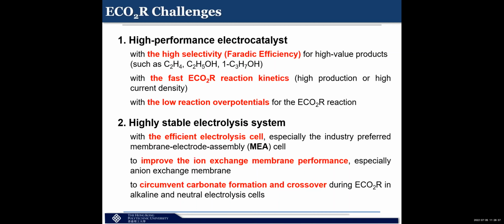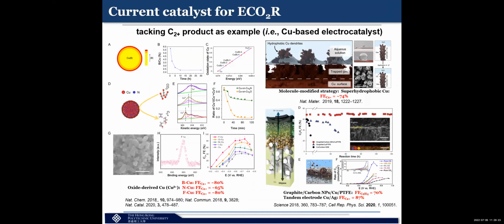But the other very important challenge is this carbonate formation or crossover in the normally electrolysis cell. They will either use alkalis or neutral type of electrolytes. So that make it very difficult to stop the crossover and stop this carbonate formation, because once the carbonate forms, it will block the cell, and then it will cause flooding, and then eventually it will shut down your cell. Okay, so the stability of the cell becomes very poor.